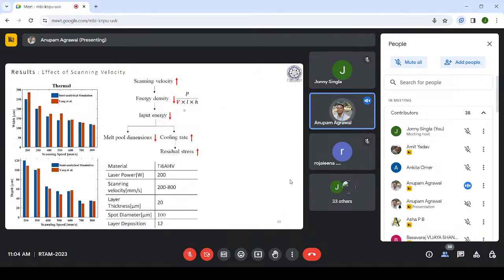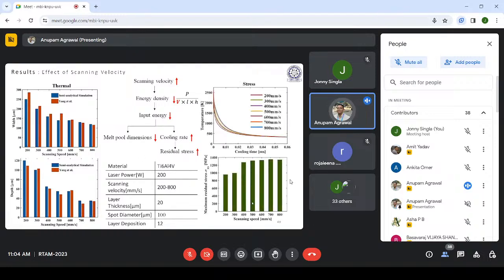Effect of scanning velocity. The other thing, which is V, scanning velocity. Now we are keeping the P and L and H the same. We increase the V, energy density decreases, input energy decreases, the melt pool dimensions decrease, and cooling rate increases, residual stresses have been found to increase. However, as we increase the scanning velocity, there is stability coming. That means after a particular scanning speed, there is hardly any change in residual stress. So the maximum residual stress is getting stabilized.